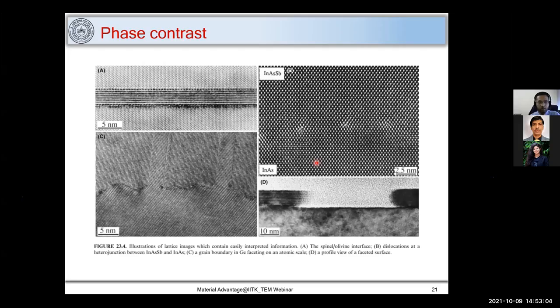Now, what is the utility of this phase contrast? We can get these lattice fringes from our sample, and we can identify grain boundaries, lattice planes, twins, and interfaces. So this is the utility of getting these high resolution TEM images, to find out where the defects are, where the interfaces are lying.